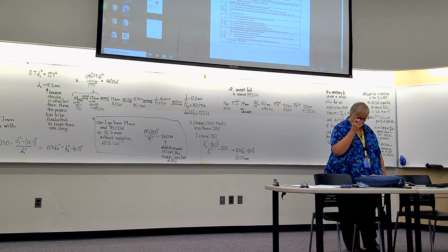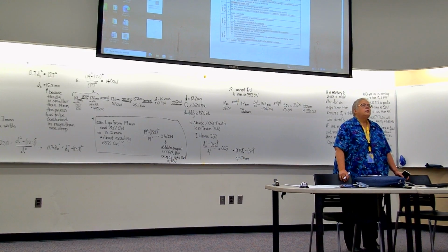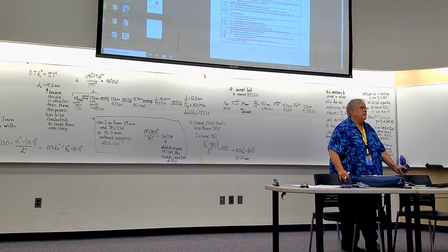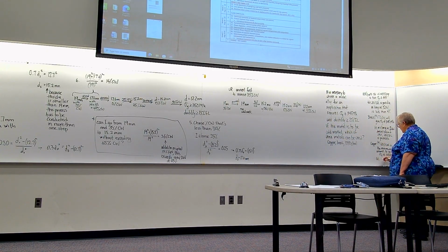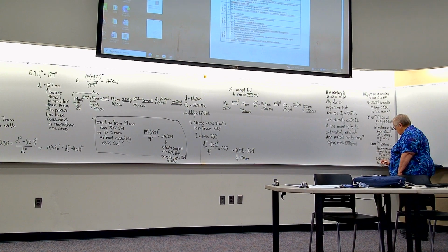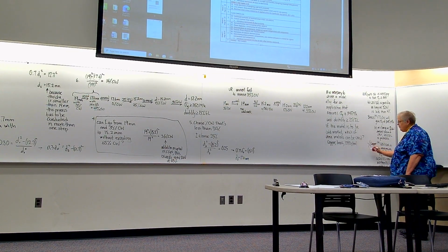To get 20% elongation, ductility on copper, how much cold work can I do? Somebody other than Ella and Tim, anybody other than Ella and Tim? Yes, cold work has to be less than 15%. That's about right. So in order to get 20% elongation, I have to have less than 15% cold work. So copper can't be used, because I can't get both the strength I want and the ductility.